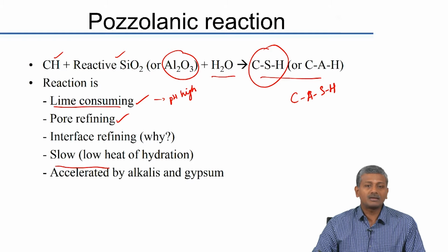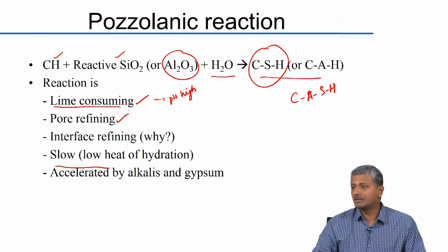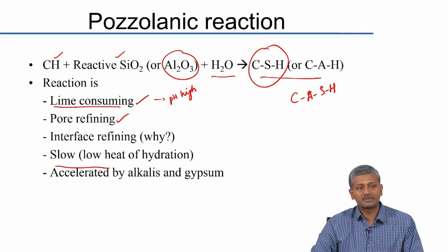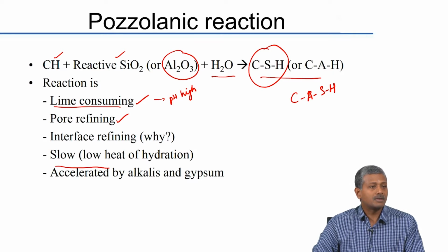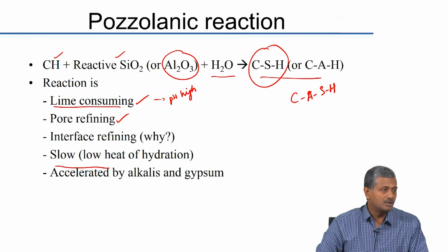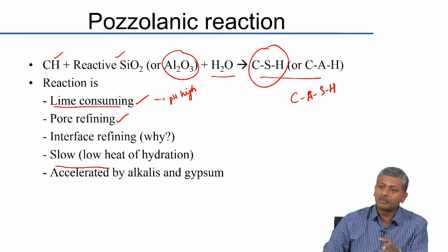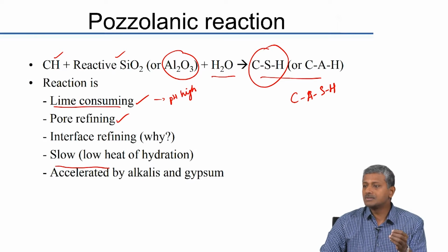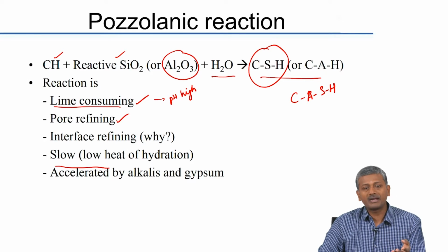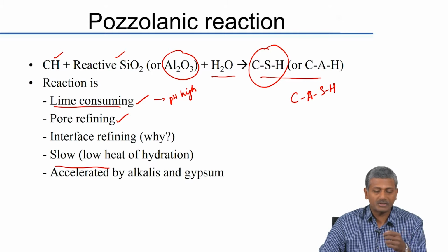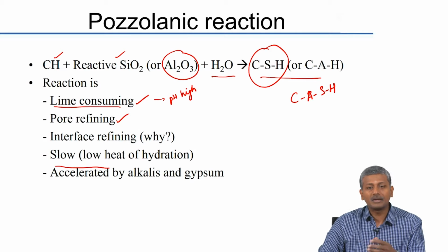So, if they cannot produce special cements, then they need to manage all these special performance requirements with regular Portland cements. For example, the low heat requirement which is there for mass concrete can also be obtained from a mixture of ordinary Portland cement and fly ash. You replace cement with fly ash, you can actually slow down the hydration and liberate much lesser heat.